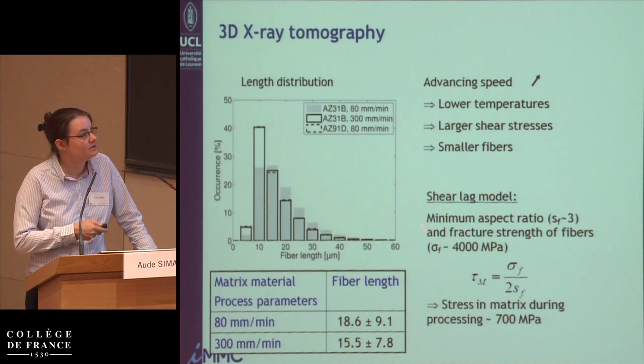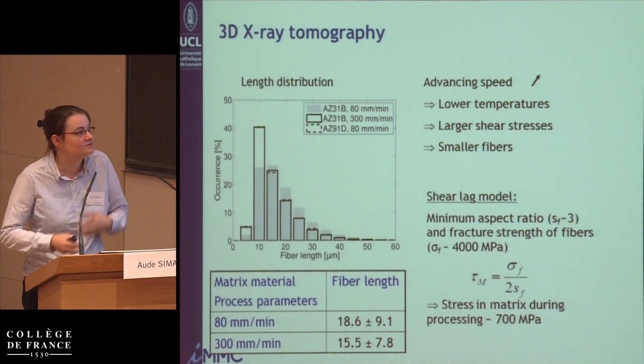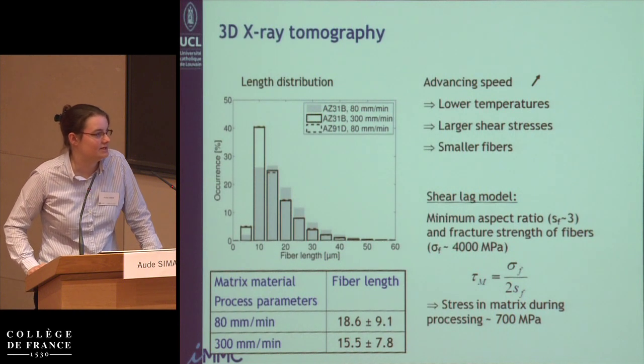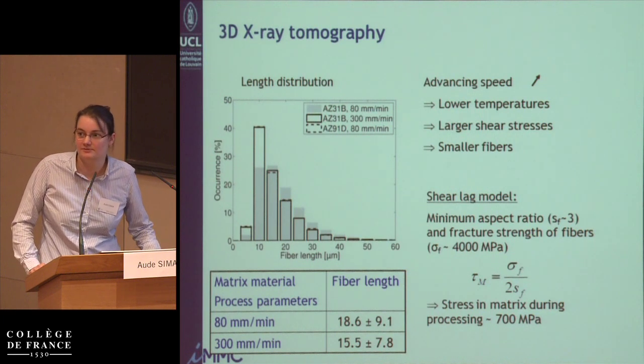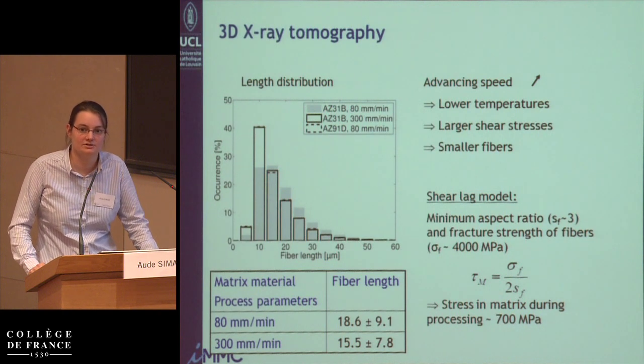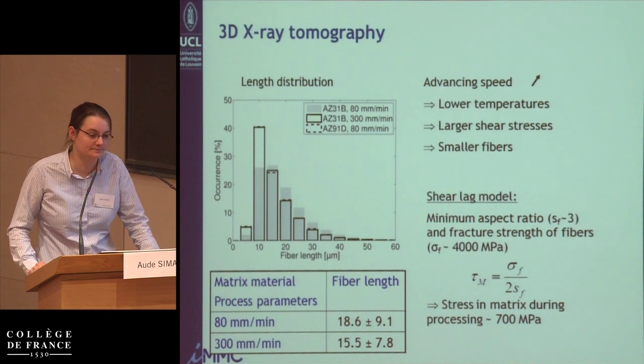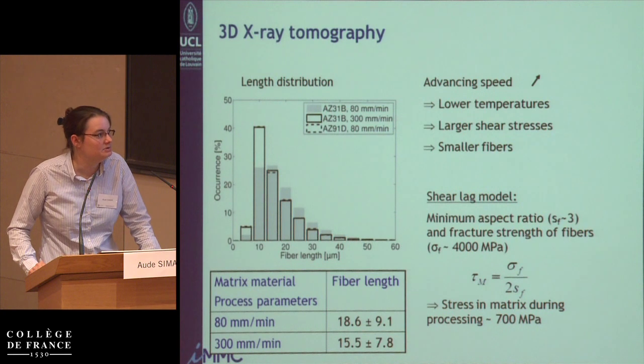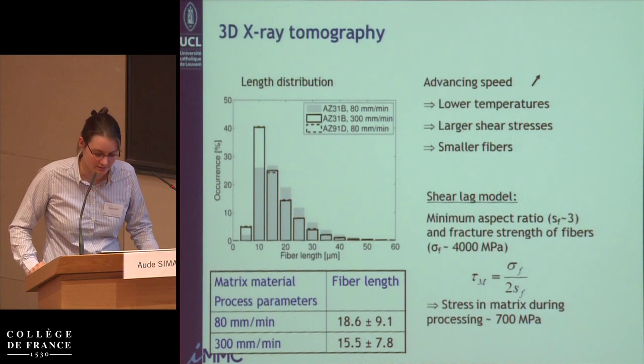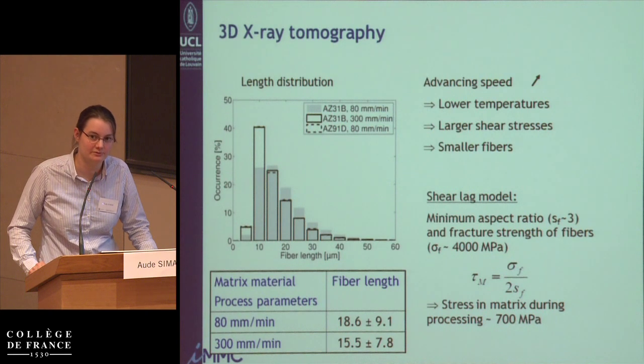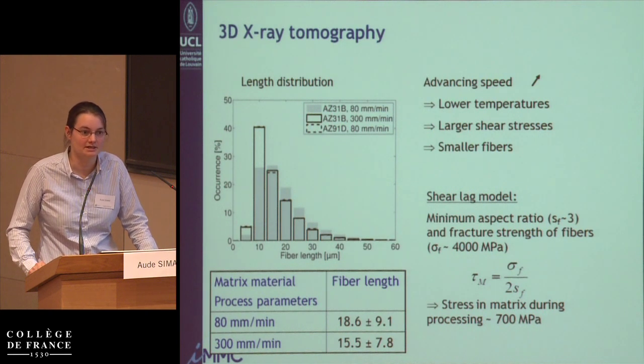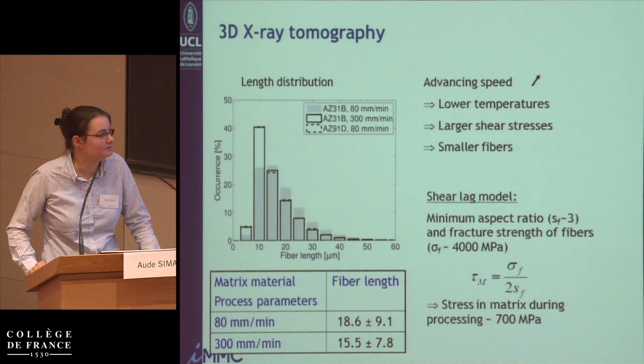And using a shear lag model that I will not detail here, you can estimate the stresses that these materials have supported, and they are estimated to be about 700 megapascals, which is very large for the temperature that we reach here. But that just gives you an idea of the kind of conditions that are associated to the very large deformations that we observe here. We don't really believe that these 700 megapascals are really relevant as a value, but that just gives you an idea that we are talking about very large deformation. Some people talk about strain rates and deformation that you can't reach by any other processing method.